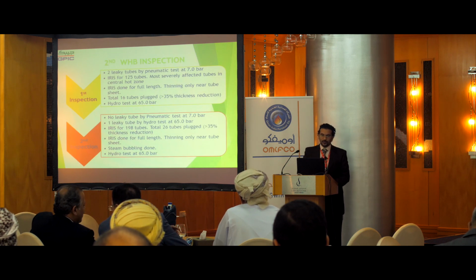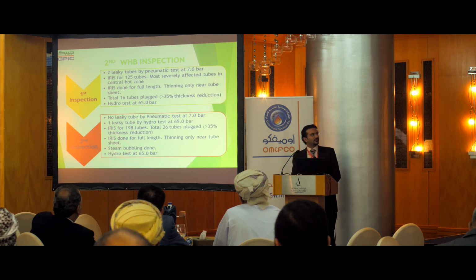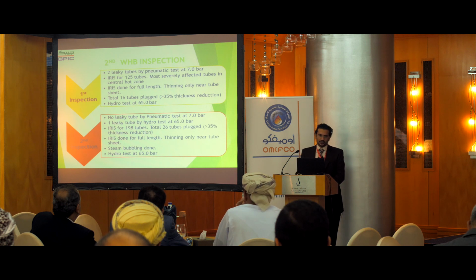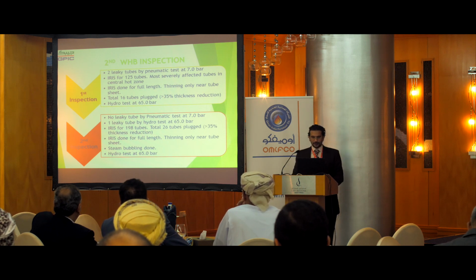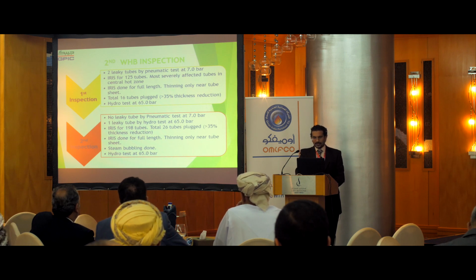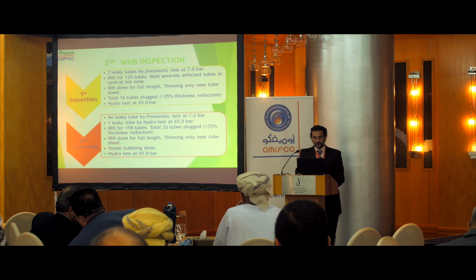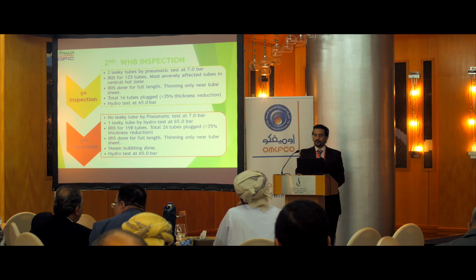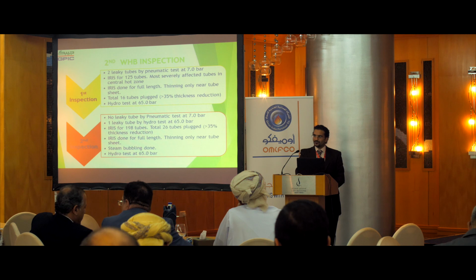Our second waste heat boiler went through several inspections after the leaks. Two leaky tubes were found the first time it was inspected, and a total of 16 tubes were plugged. Hydro tested at 65 bar later on, it was found okay. Second inspection, there were no leaky tubes, and we did the internal rotational inspection for the full length. There was only thinning near the tube sheet. Steam bubbling was done, and the hydro test.